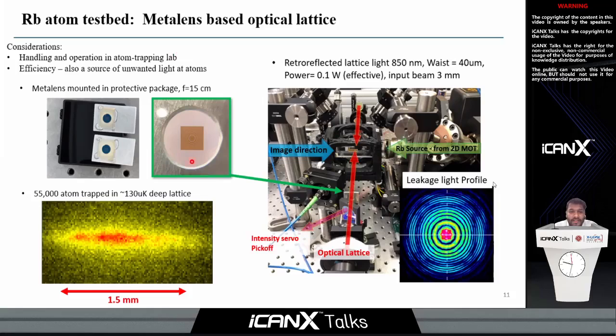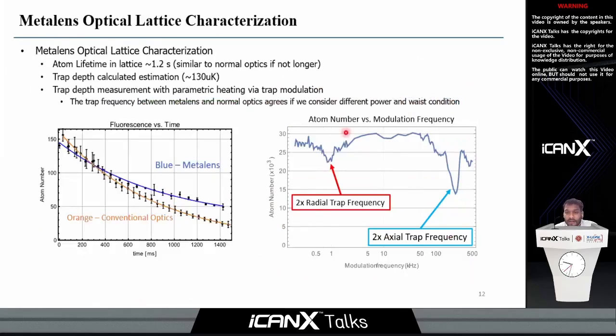So before one jumps the gun on trying to use these, one has to consider all these aspects. So what we decided was a simple experiment where we said, okay, why don't we try to make a MOT out of a metasurface in a lattice configuration. So shown here is a picture of a rubidium MOT that was brought to the location of the center of these red arrows, and then this rubidium MOT was put in this lattice configuration using this retro-reflected beam, and one of the lenses in this retro was replaced by a metalens shown here, and indeed what they showed was that we are able to trap an ensemble of atoms in a 130 microkelvin deep lattice.